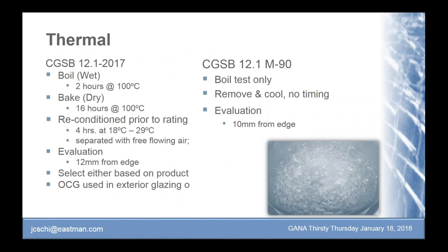The thermal test is new, at least the bake part of it. The boil test is 2 hours at 100 degrees C. The bake test is 16 hours at 100 degrees C. You recondition it to the temperature range prior to rating, and you evaluate anything that occurs that is outside of the 12 millimeters from the edge. And that's very consistent with obviously Z97. And you can see the changes. The 90 version had boil test only. You removed it and then rated it at various times. Essentially, as soon as you could handle the glass, you could rate it. And the evaluation area from the edge was a little bit smaller.